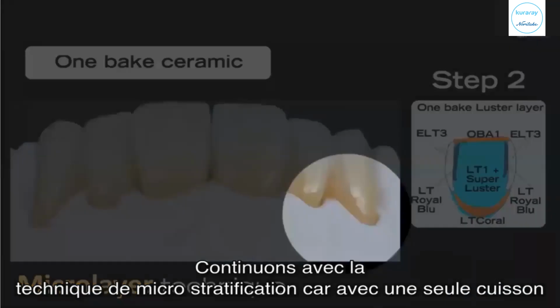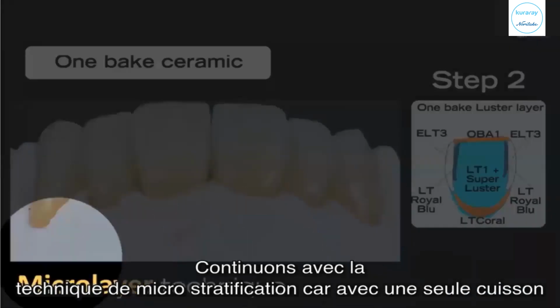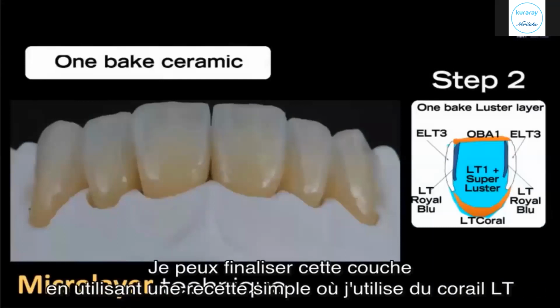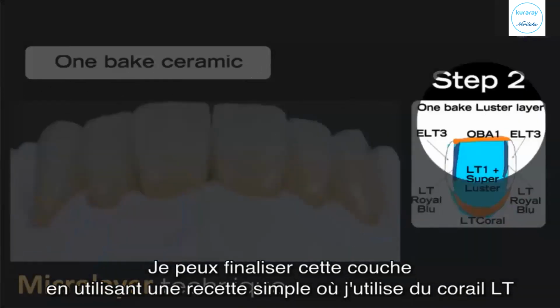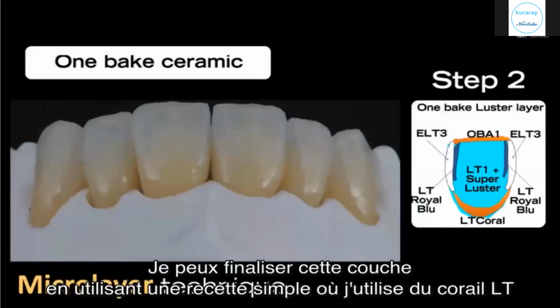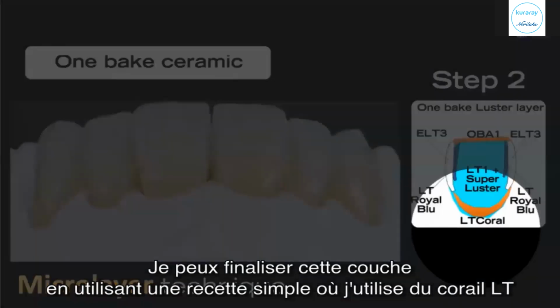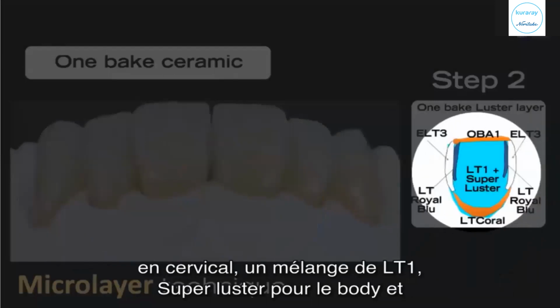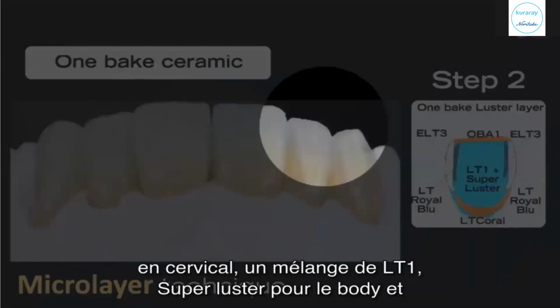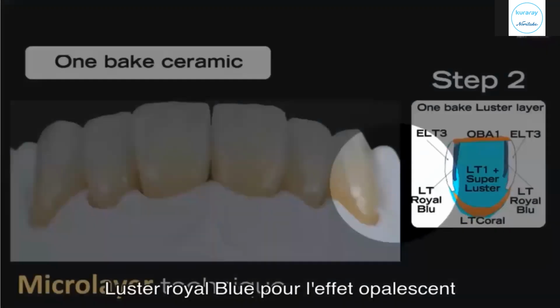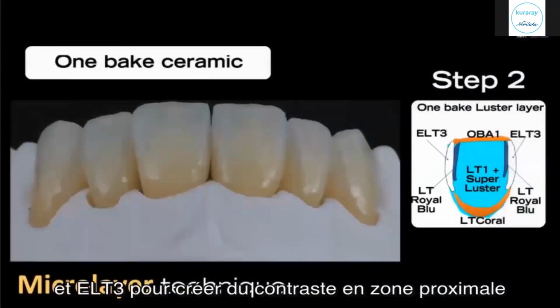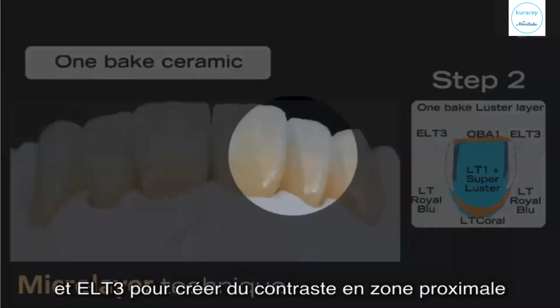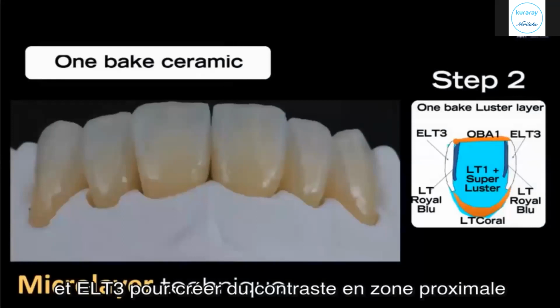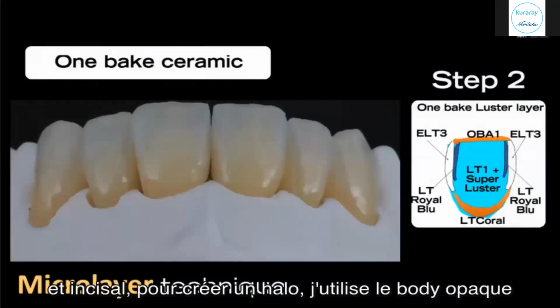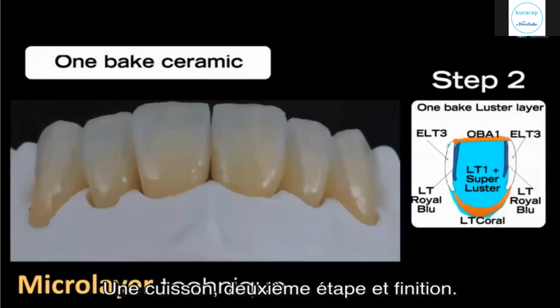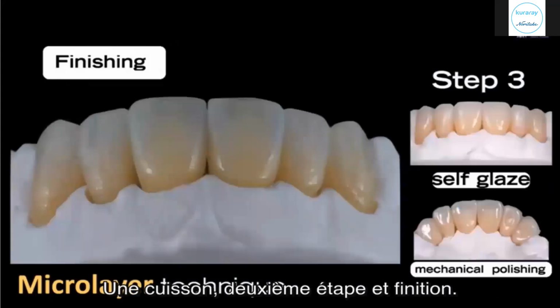Now I want to apply this with the micro layer technique, because in only one bake I can finalize the layer using a simple recipe where I use LT coral cervically, one mix of LT1 and super luster for the body, and luster royal blue for the opalescence effect, and ELT3 to create a contrast area proximally. And in the incisal, to recreate the halo, I use the opacious body. So one bake, second step, and finishing.